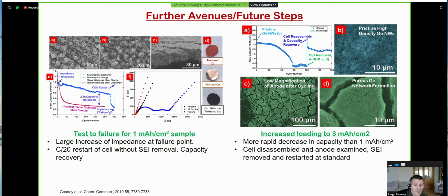So what we did was we removed the SEI from there and reassembled the cell within a new fresh half cell and started the cycling again, and this capacity jumped way back up again. So in this case, the issue was actually due to the lithium counter electrode. So essentially what we had was a failure of the lithium counter electrode, and once we had reassembled the cell there, our capacity drastically improved.